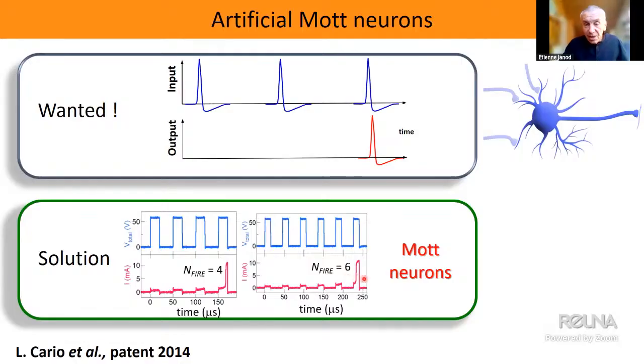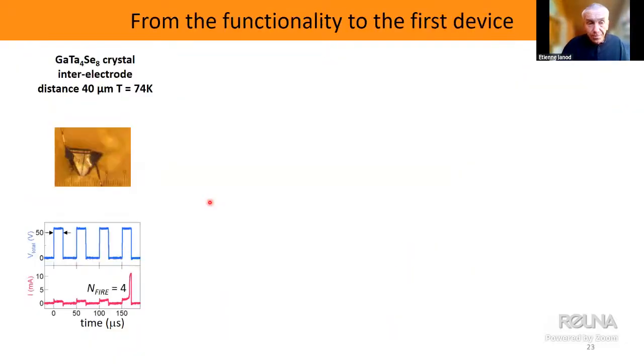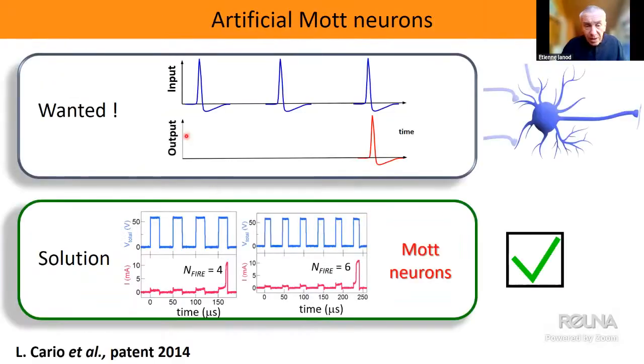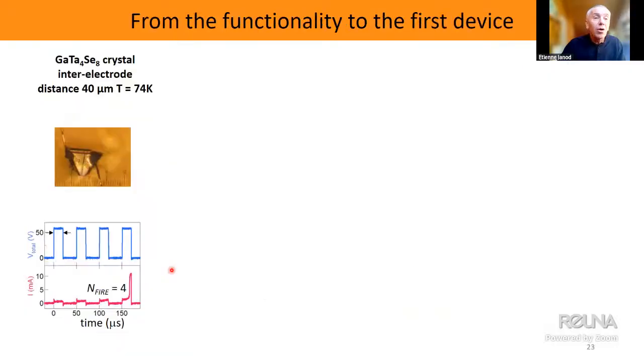So this is interesting because it's a proof of principle that we can implement artificial neurons out of Mott insulators. Of course, you might have noticed that the voltages that I apply are extremely high, 50 volts, and currents are also very high. Moreover, these experiments were obtained at low temperature. So it's not really useful for microelectronic applications.